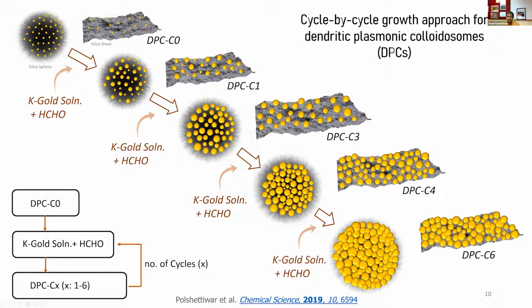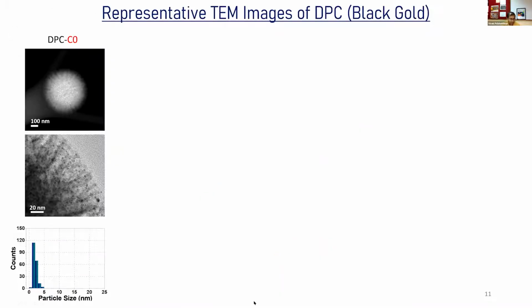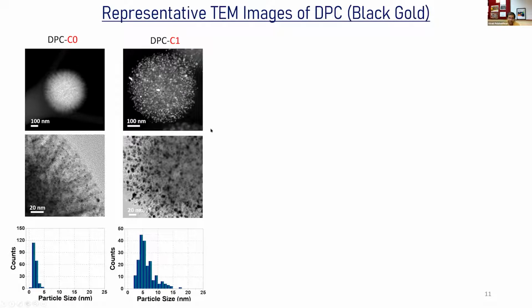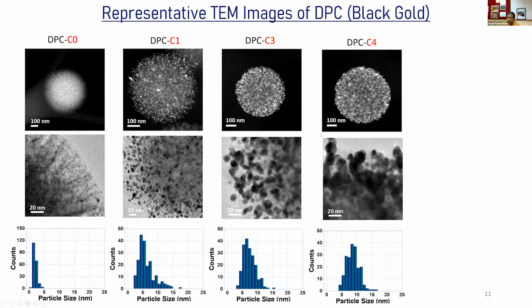It has this dendritic structure, so the gold nanoparticle which is inside will receive less gold precursor as compared to a gold nanoparticle on the surface. So we had some sort of heterogeneity in the gold nanoparticles, but heterogeneity in a plasmonic system is a good thing, because the more heterogeneous the system, the more hotspots you have that you can use to carry out the catalysis. So you see the TEM images. This is the C0 small gold nanoparticles dispersed onto the silica surface, and then we have C1, C2, C3, C4.